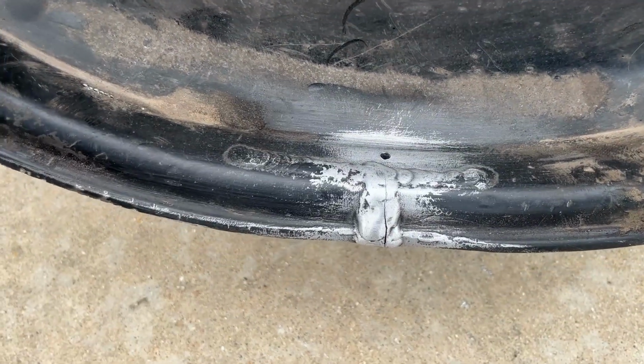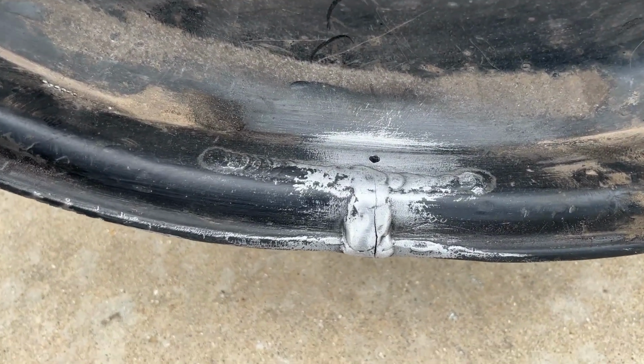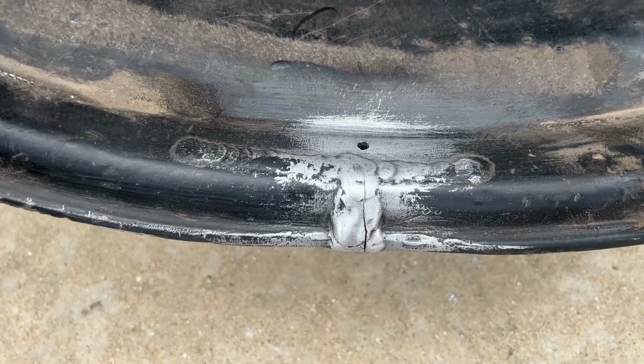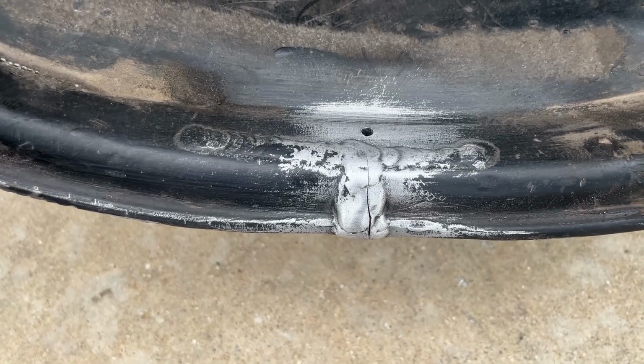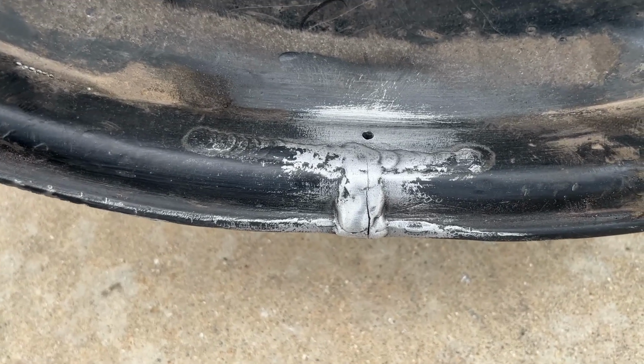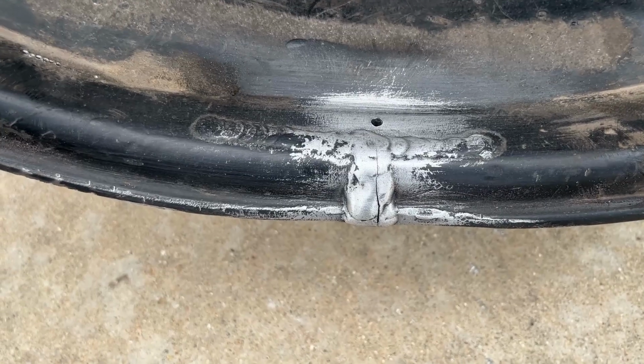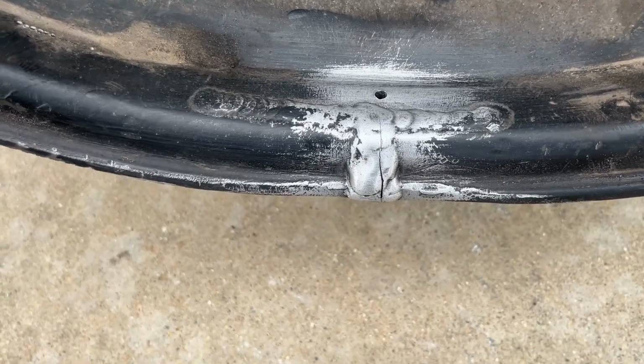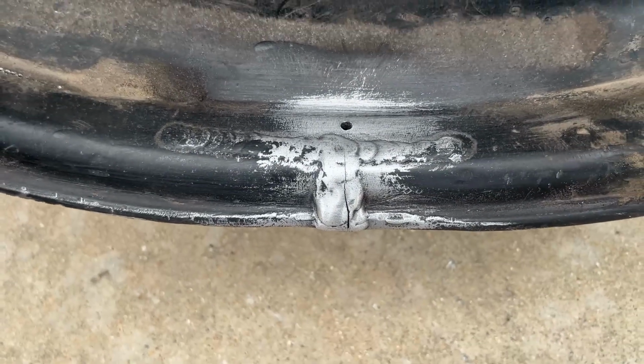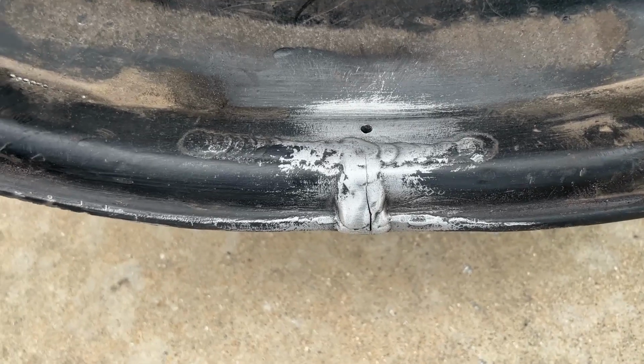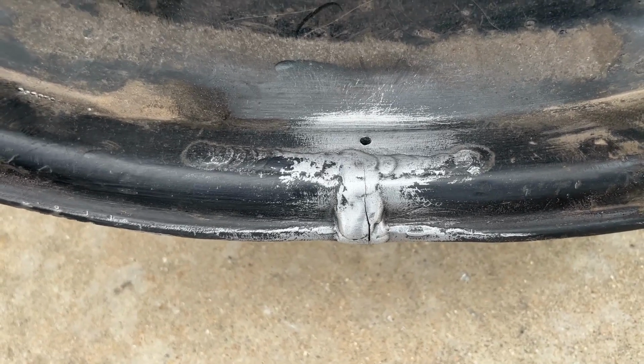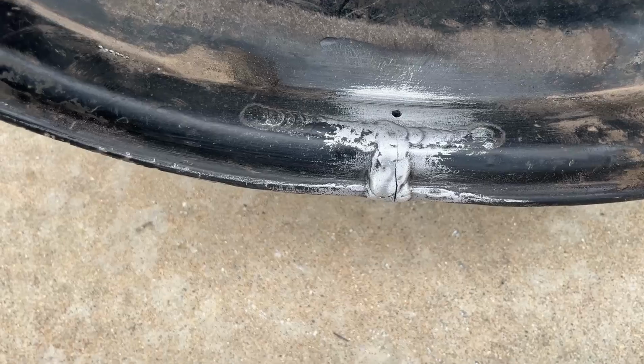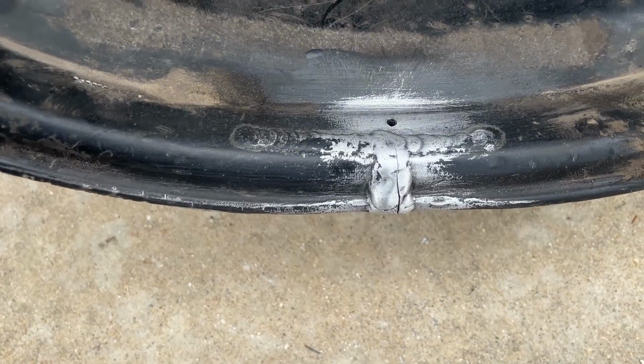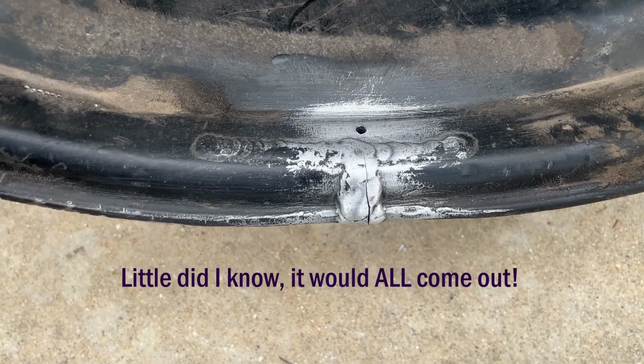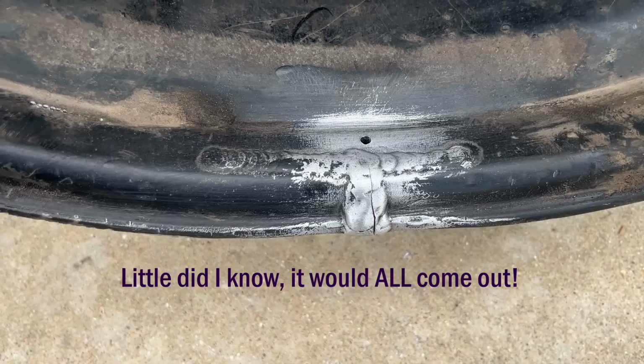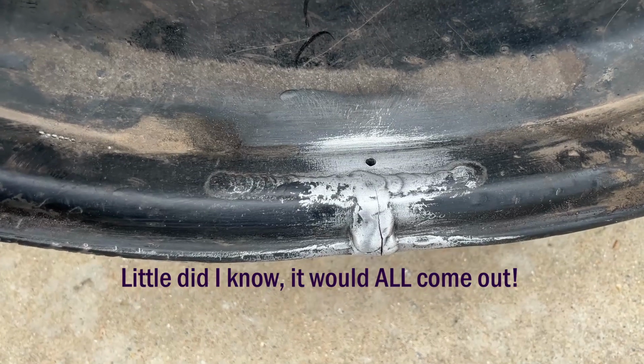That's not good either. Because any place we've got a crater that's unfilled, there's a potential for cracking to occur. Because an underfilled crater places the crater in tension, and a filled crater puts the crater in compression. And most things are stronger in compression than they are in tension. So this makes me think we got to hog as much of that weld off that we can and get back to some relatively undisturbed base metal underneath of it.